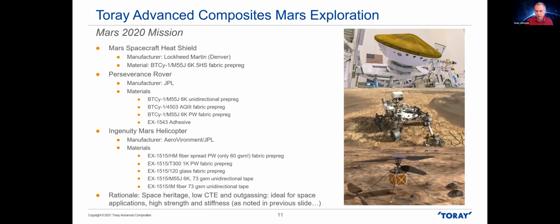A whole suite of materials there that were used to do the composite work. You probably noticed on Ben's pictures of the blades, they're shiny, of course, so they have very good surface and contributes to lower drag and lower aerodynamic loss. Also very, very thin plies, so you can balance the stresses within the laminates. And you probably noticed that the surface looked like it was a series of squares, and that's the spread fabric with the high modulus fiber that you saw.